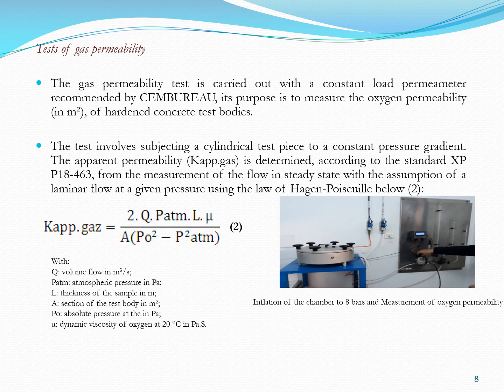The gas permeability test is carried out with the constant load permeameter recommended by Cembureau. Its purpose is to measure the oxygen permeability of hardened concrete test bodies. This is a laboratory method applied to model and core test specimens of structures within the limits of the dimensional tolerance imposed by the measuring cells of the device. The test consists in subjecting a cylindrical specimen to a constant pressure gradient. The apparent permeability is measured according to the standard.